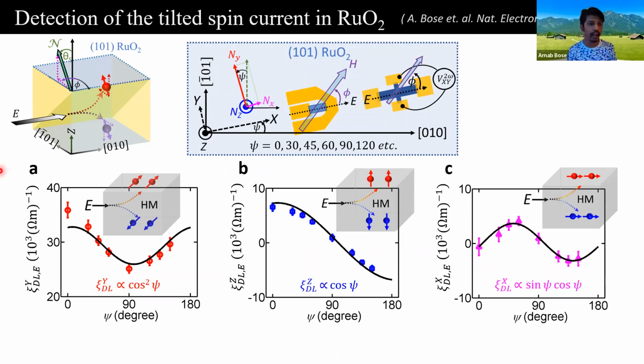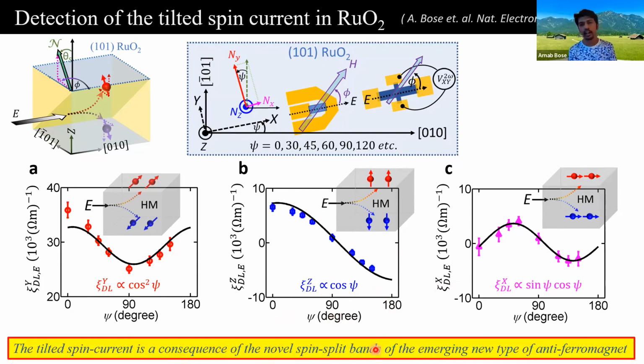So this clearly suggests that we have tilted spin current generating in the 101 ruthenium dioxide film that strongly depends on the direction of current flow with respect to crystal axis. One important thing to note is that here we have an offset in the Y polarized spins. This offset indicates that on top of this extraordinary spin current, we have regular spin Hall effect. That spin Hall effect would even exist if there is no magnetic ordering. However, this specific angular dependence strongly suggests that it originates from the novel spin split bands of the emerging new type of antiferromagnet, ruthenium dioxide.